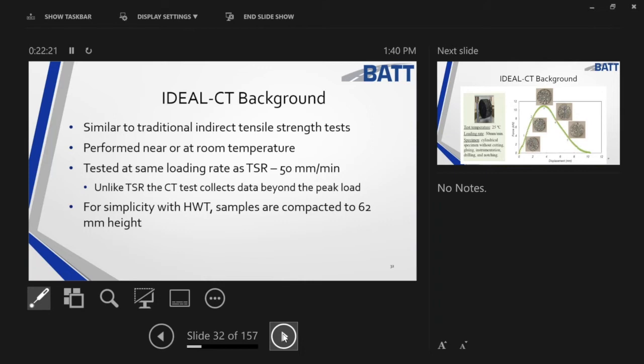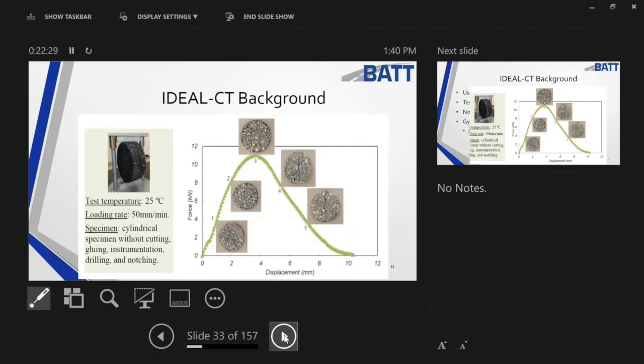Now, I would tell you, you want to go a little thicker than that once you get into 3/4 inch mixtures and larger. So as I begin to crack the sample, as you see here, as I move, these slides are borrowed from Fuji Zhao down at Texas A&M, and I appreciate all of Fuji's hard work on this and moving this through the ASTM committees to get this test out there for us. There's a lot of work to be done on the test, but this test has given us so much good feedback. Now, Fuji runs it at 25C. In Kentucky, we're going to run it at probably 25C with a little different limit, but if you go to Ohio, you may see them running it at like a 21C or lower.